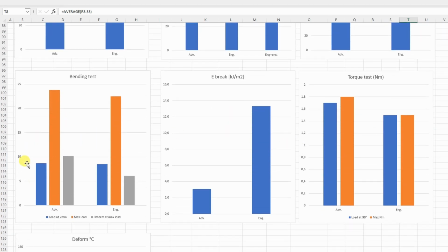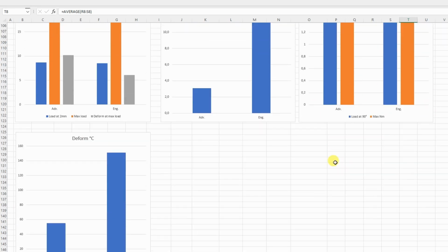The bending test was again very similar, only I can see that the engineering PLA resists more, so on this very similar load it deformed only 6 mm compared to the 10 mm deformations with advanced PLA. Now on the impact test we can see very significant differences, so engineering PLA is an extremely tough material compared to the advanced PLA or to other PLA materials. The torque test was very similar in both cases.